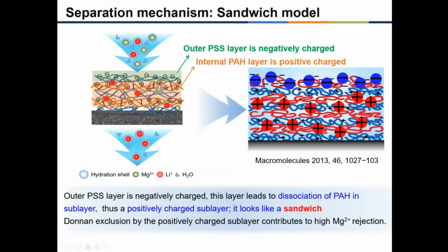For the 2.5 bilayer PSS-PAH ending with PSS, the outer layer is a strong polyanion. The outer layer is negatively charged. This layer leads to dissociation of PAH in the sublayer, resulting in an internal structure with positive charge. We estimate that our PSS-PAH multilayer has a negatively charged surface, but with a positive internal structure. It looks like a sandwich. Donnan exclusion by the positively charged sublayer contributes to high magnesium rejection.